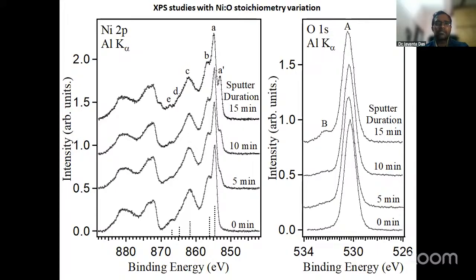And when we did the XPS studies, the X-ray photoemission spectroscopic studies, we also find that with higher bombardment, let's say from 0, this is the result of 0 minutes, that means the as-deposited sample, then the argon ion bombarded sample for 5 minutes, 10 minutes and 15 minutes, we can see a small tail that gradually rises up, this A prime peak. This corresponds to the nickel peak. That means the sample partially has some metallic nickel that appears with the argon ion bombardment, and there is an oxygen reduction. When we quantified, we find that almost 13% metallicity we can get upon argon ion bombardment.